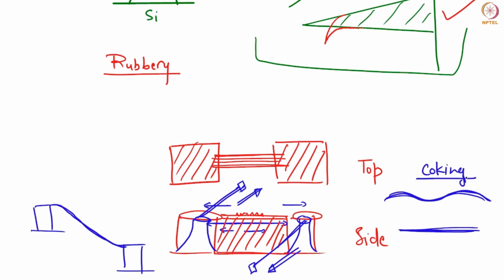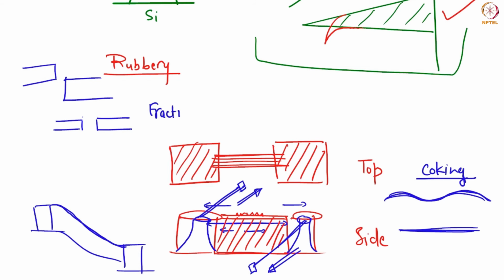If you have a polymer which, rather than twisting or bending, breaks, so if you had a coking kind of mechanism, then let's say whatever was your fiber, that breaks. Or if you had the wall, it does not really show bending, but two separate structures like that. So if there is any kind of fracture in the structure, in that case you can say that this is your coking process. So basically, these are some of the simple experiments that you can perform.